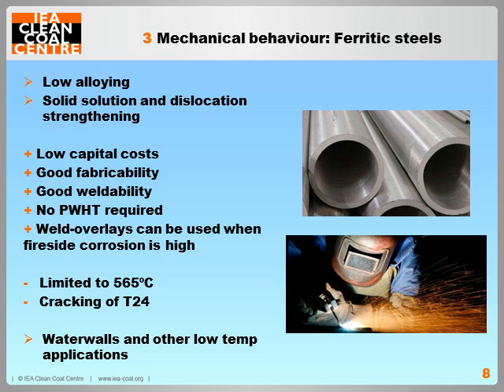Ferritic steels made up most of the components in subcritical pulverised coal-fired power plant, and the chrome alloy ferritic steels such as T22 are used in water walls and other low-temperature applications in supercritical pulverised coal-fired power plant. The installation of low-NOx burners in boilers has caused excessive corrosion of ferritic steels near the burners due to differences in combustion stoichiometry. This problem has been solved with protective high chromium weld overlays.